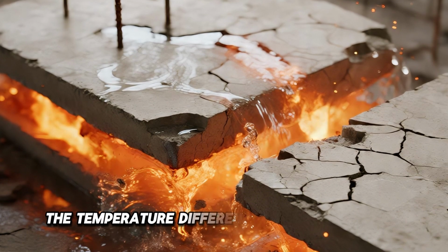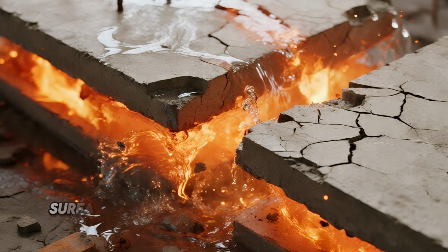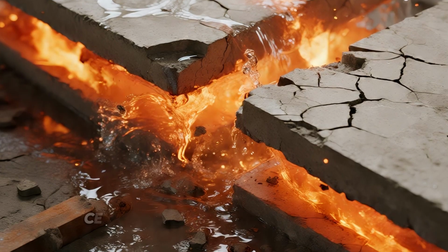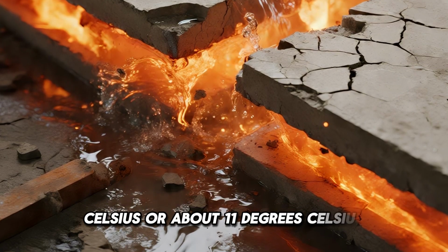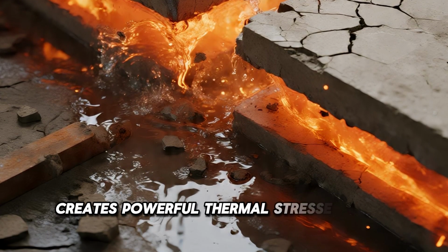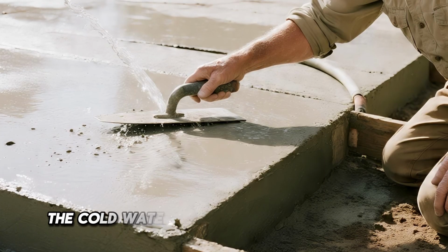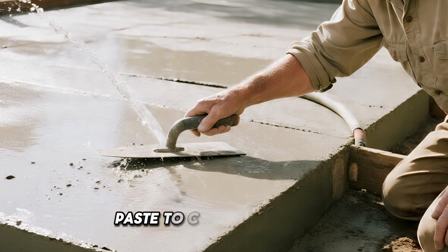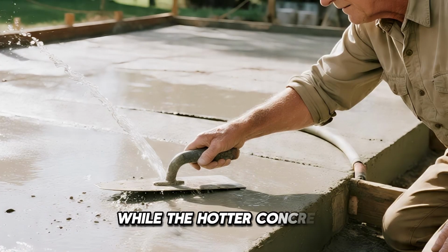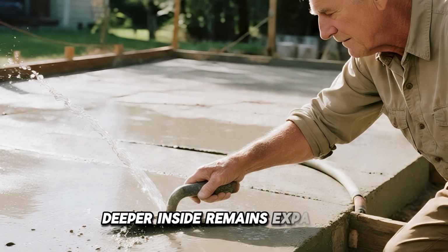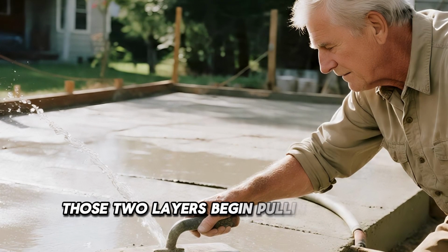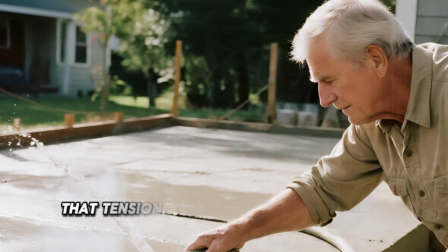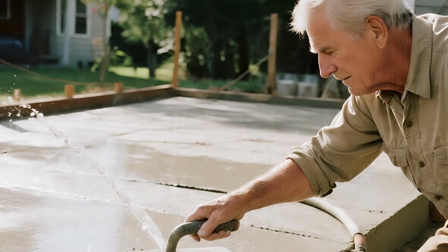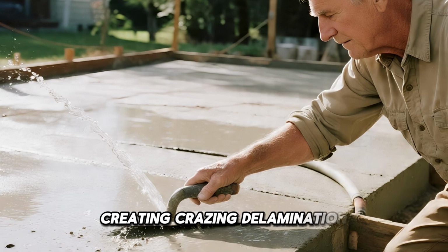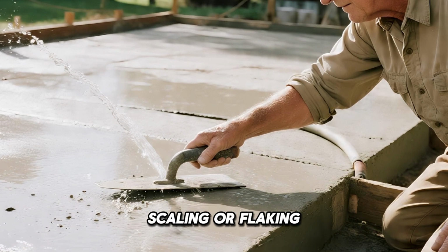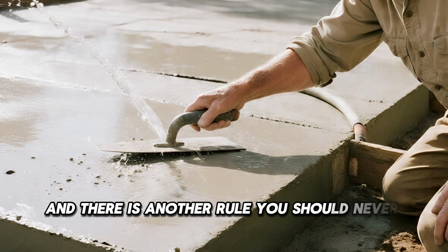The temperature difference can be enormous. A rapid surface temperature drop of more than 20 degrees Fahrenheit, or about 11 degrees Celsius, creates powerful thermal stresses inside the slab. The cold water forces the delicate surface paste to contract quickly, while the hotter concrete, deeper inside, remains expanded. Those two layers begin pulling against each other. That tension can tear the weak surface apart, creating crazing, delamination, scaling, or flaking. And there is another rule you should never forget.